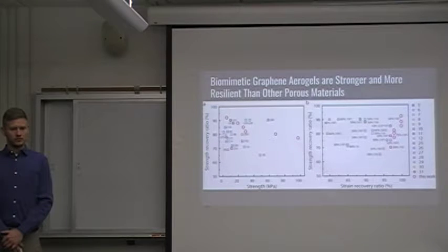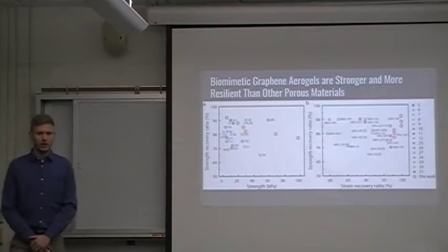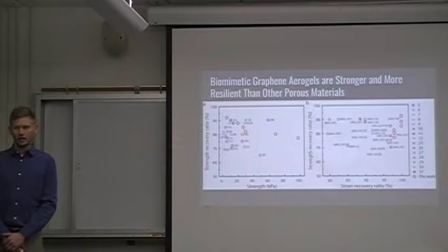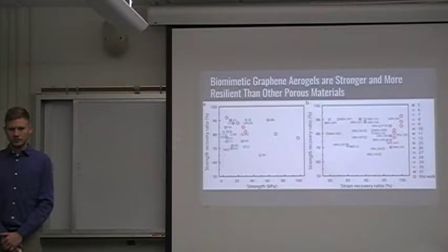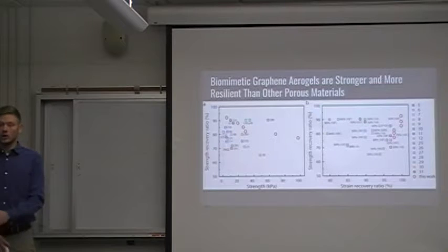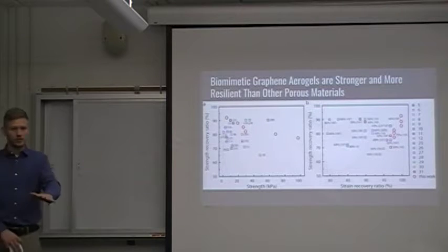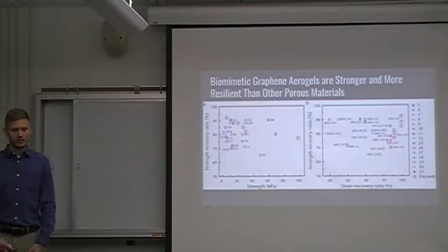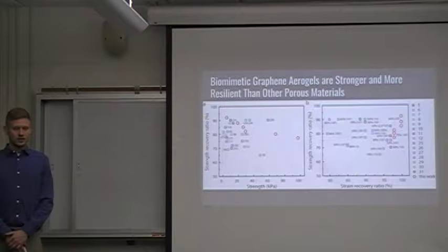And then you talked about reducing the graphene oxide to graphene. How do you do that again? In a chamber of 98% argon and 2% hydrogen at 800 degrees Celsius. Did you say 90% oxygen? No, sorry, argon. No oxygen, because you can't reduce. That's good, otherwise you'd have fire on your hands.